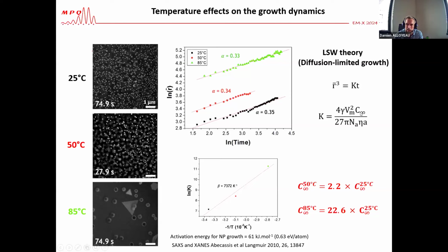And in this growth constant, we have the equilibrium solubility. So we can quantify the change in solubility of the solution with temperature, and we obtain these different values. You see that the solubility increased 22 times from 25 to 85 degrees.